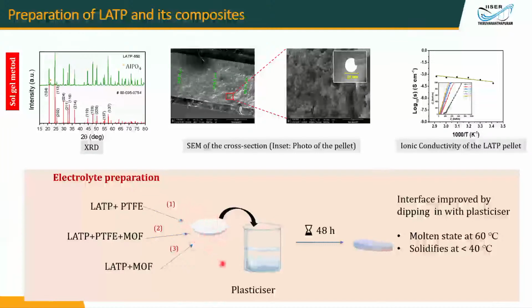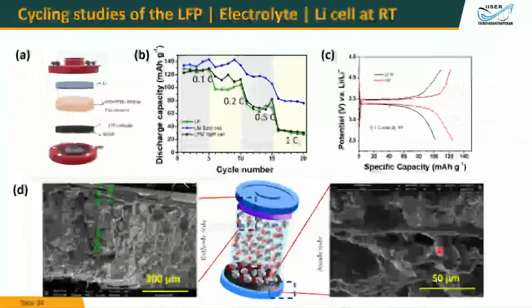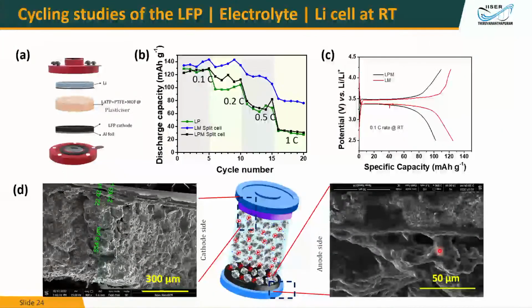So we made them into a pellet, and then we added them to a plasticizer, which I am not going to reveal because this work is not published. We just kept it in the plasticizer solution. That solution is liquid at 60 degrees, and it solidifies at 40. So we add these pellets inside the plasticizer and leave it for 48 hours, and then take it out at room temperature, and that becomes a solid electrolyte. That solid electrolyte was used in combination with the LFP and the lithium, and we were able to achieve good capacity.